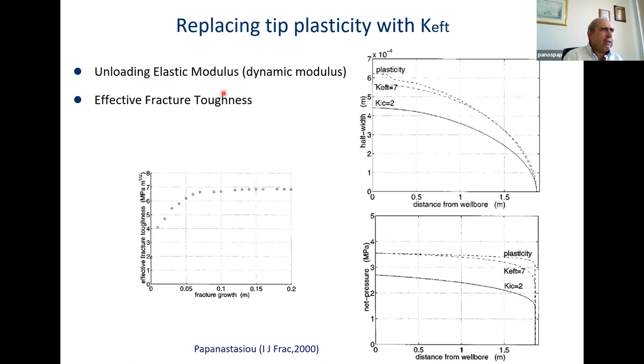So to use the unloading elastic modulus, which is very close to dynamic modulus and actually quite easily available in the petroleum industry, and to take care of plasticity with effective fracture toughness. To show that, I have one of the diagrams which shows the calculation of the effective fracture toughness with fracture length. I will take the limit value here, and I will use this limit value in the elastic simulator, and then compare the results with the full plasticity model.